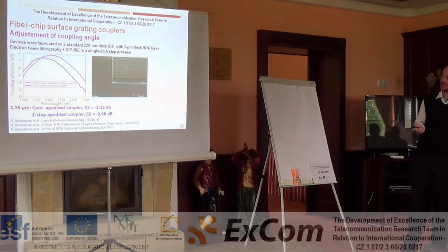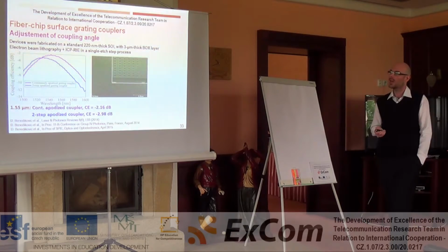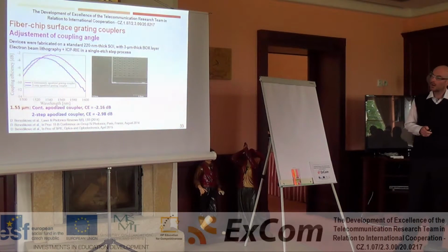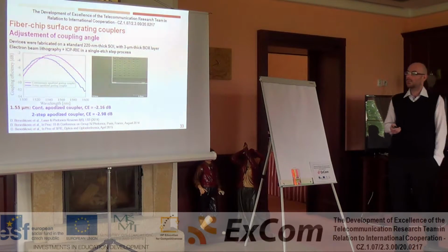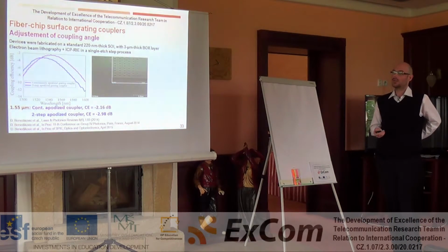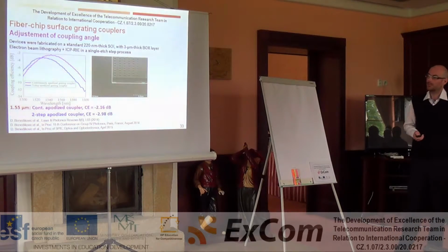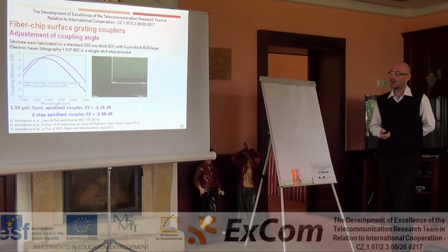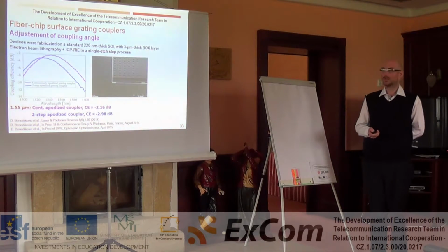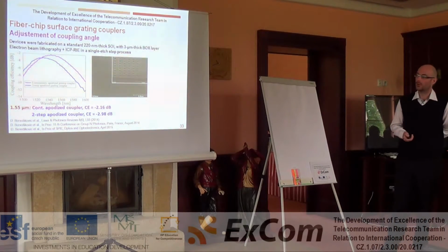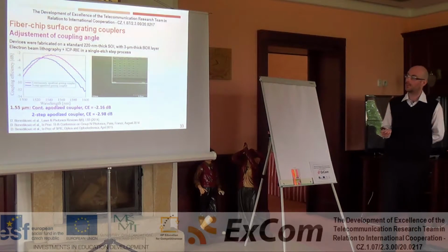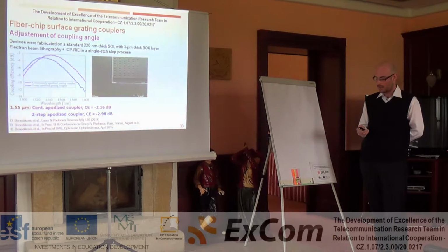These grating couplers have been fabricated by using electron beam lithography and inductively coupled plasma reactive ion etching by using only a single step process. We achieved very high coupling efficiency, which is actually one of the highest achieved to date for surface grating couplers implemented in silicon on insulator waveguides.